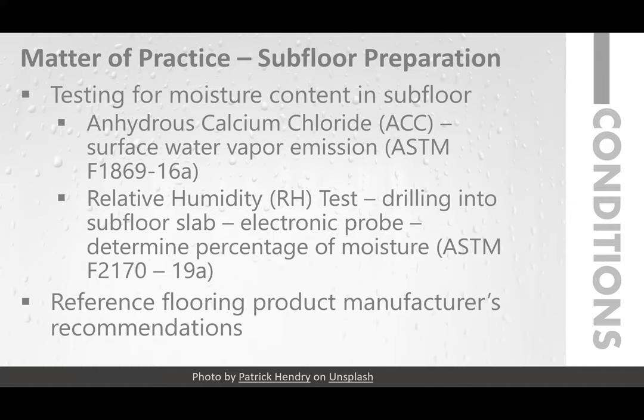Best practice is to do both tests because they test things slightly differently and in different locations. The cost of requiring both tests is not substantial. Calculating relative humidity levels allows identification of the most appropriate adhesives based on site conditions. For example, many standard flooring adhesives are rated to withstand up to 80% relative humidity; if installing in a more humid environment, a different product or moisture mitigation solution must be specified. Always reference a specific product manufacturer's recommendations for the recommended adhesive based upon site conditions.